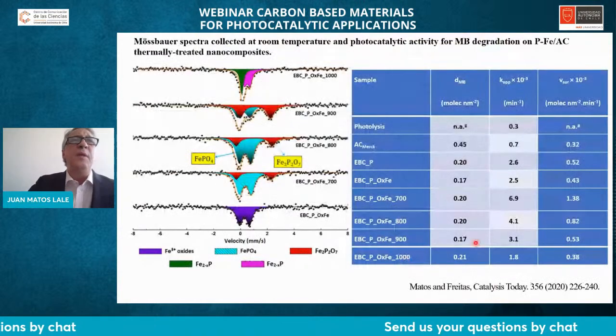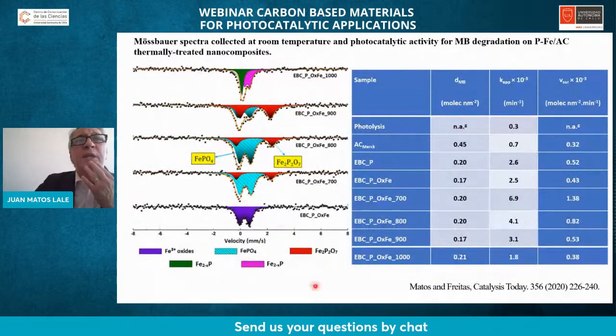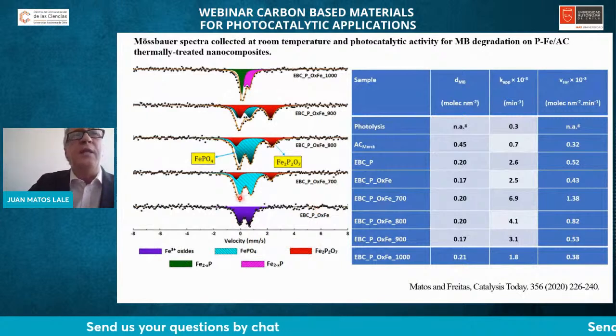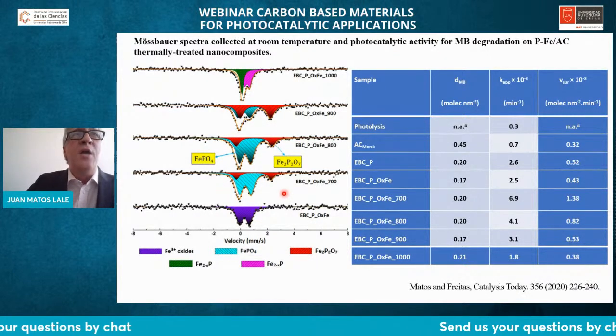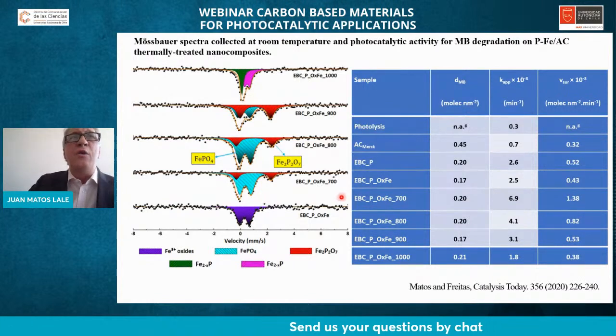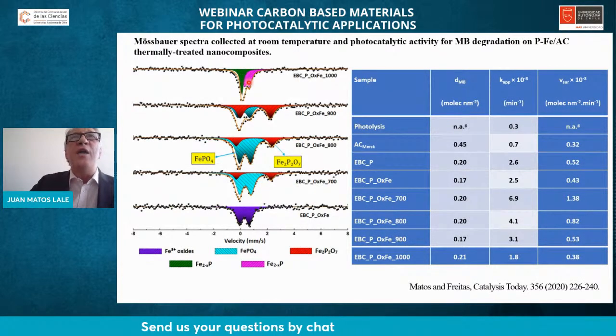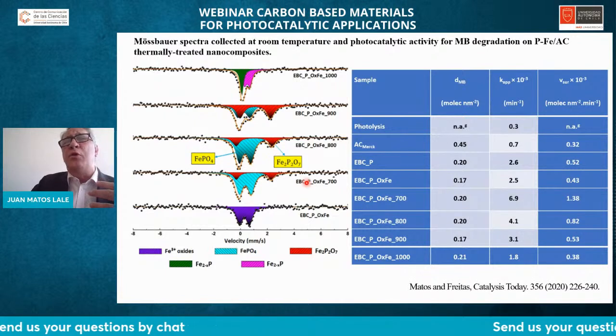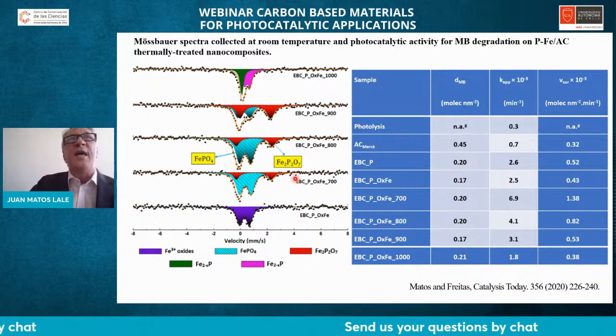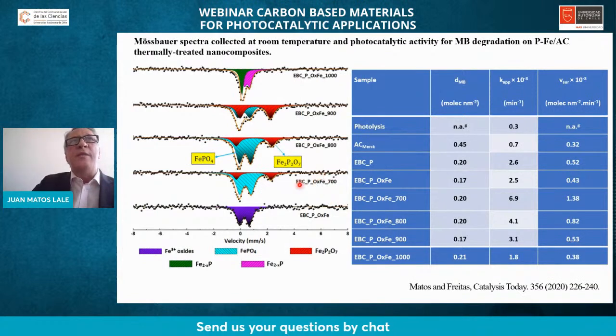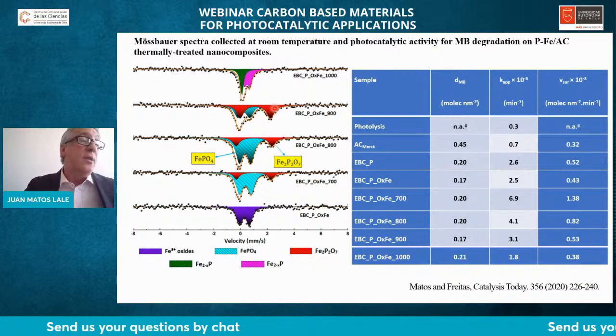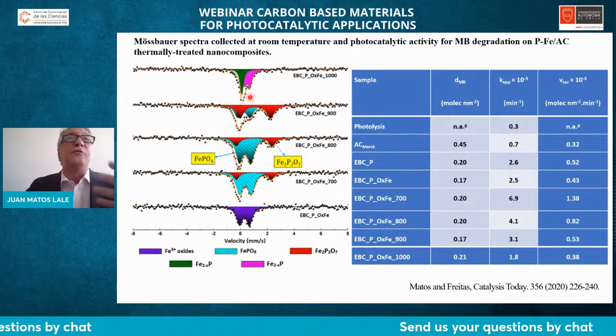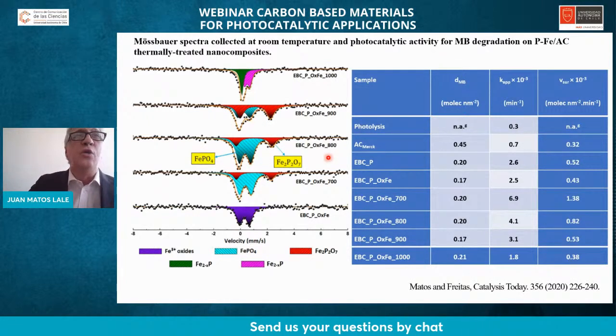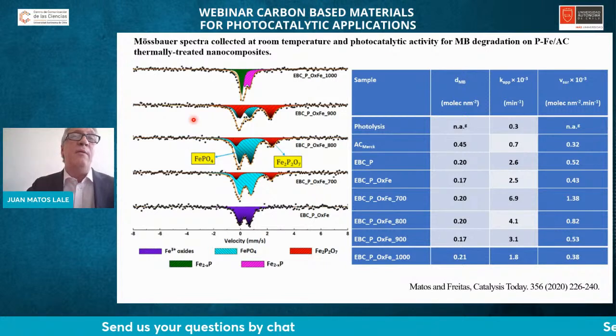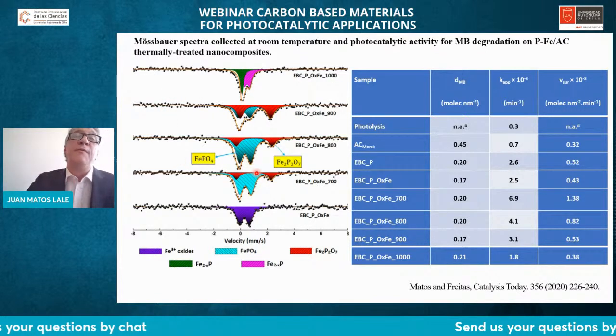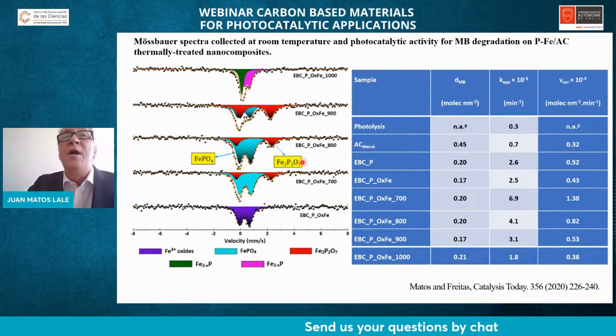So then we dealt a little bit with phosphorus-doped materials, and we were able to control the possibilities to form iron phosphate, iron pyrophosphate, or even iron phosphides. We are able to introduce the formation of phosphates, pyrophosphates, and phosphides. And we have already demonstrated that phosphides are not good for oxidation. That is what was expected, because in this case, carbon is very reduced and phosphorus is very reduced too. So these kinds of materials will be very able for the reduction of molecules, for the case of hydrogen photoproduction, but for the oxidation are not good.